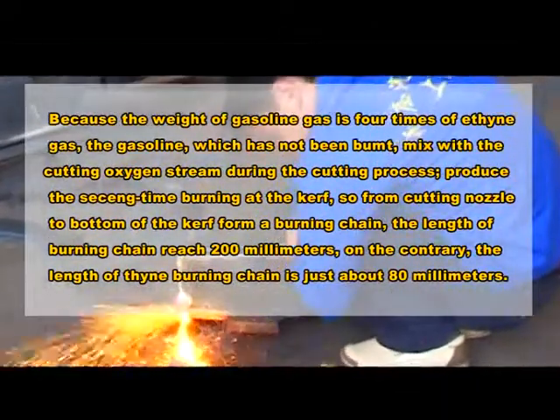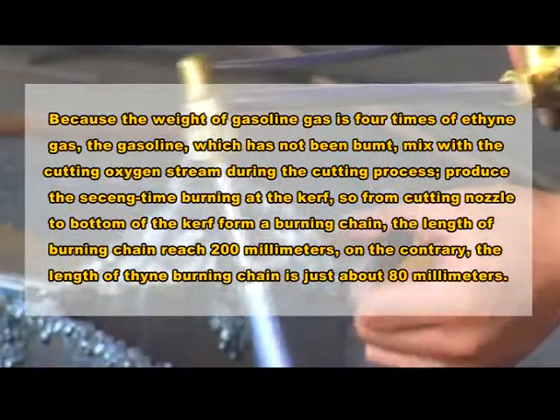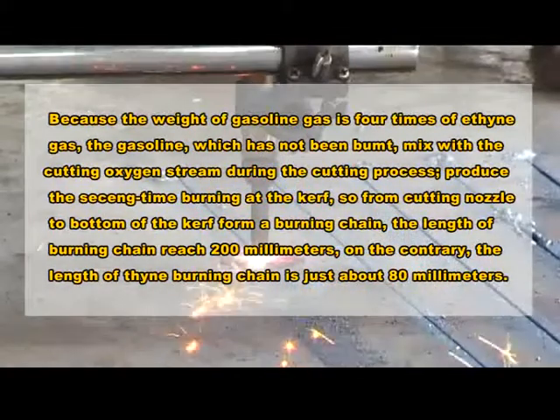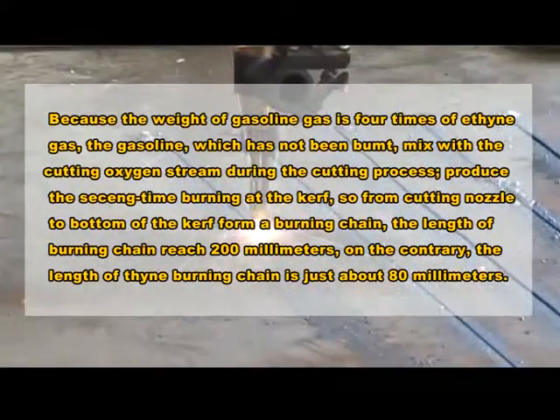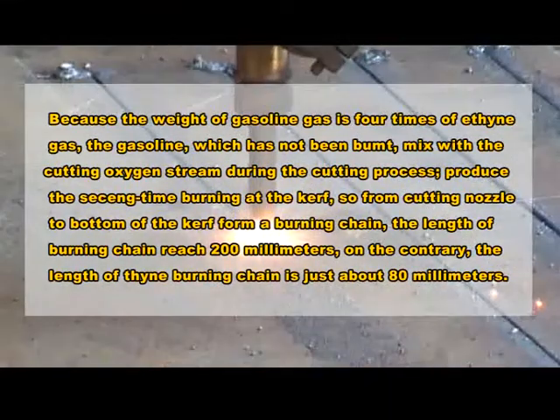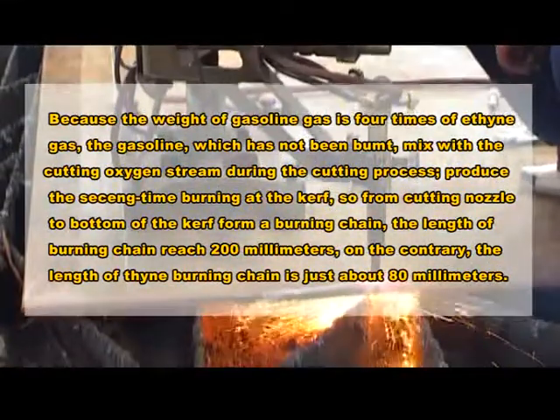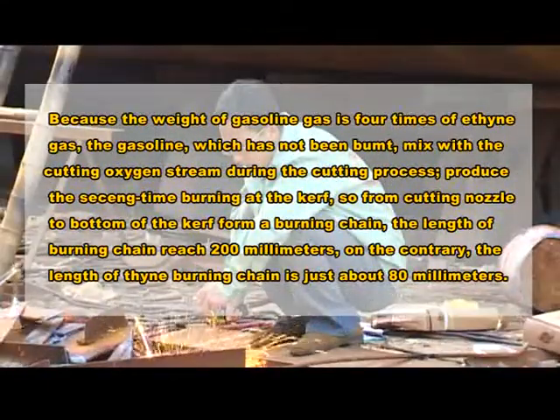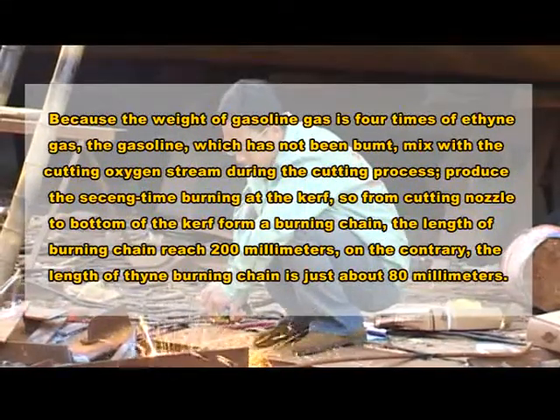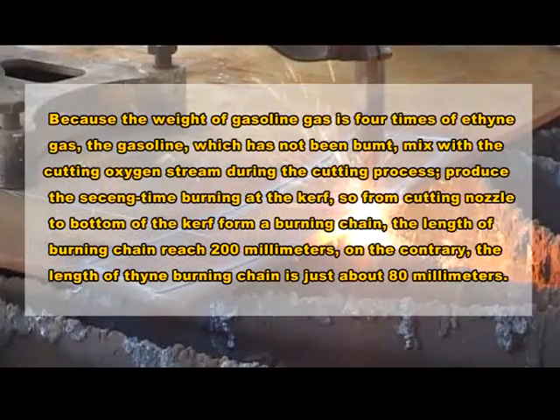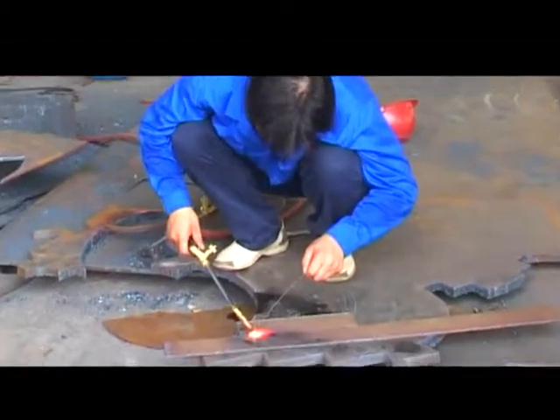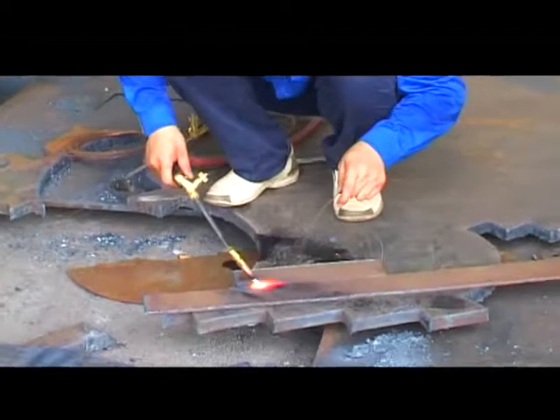The gasoline which has not burned mixes with the cutting oxygen stream during the cutting process and produces a second burning at the kerf. So from the cutting nozzle to the bottom of the kerf, the length of the burning chain reaches 200 millimeters. On the contrary, the length of the ethyne burning chain is just about 80 millimeters. This is why, when the cutting steel sheet is thicker, the gasoline oxygen cutting speed is higher than the ethyne cutting speed. The welding torch can weld a 1 to 5 millimeter steel sheet.